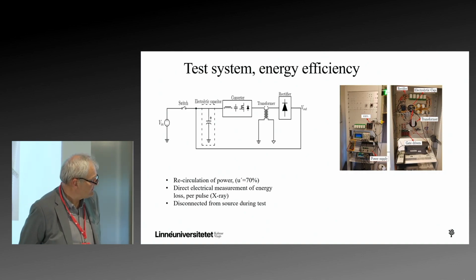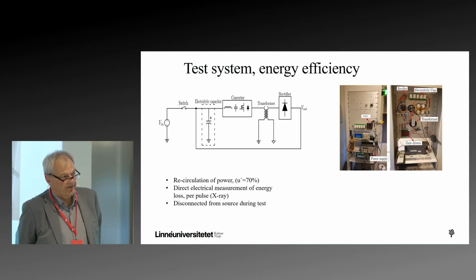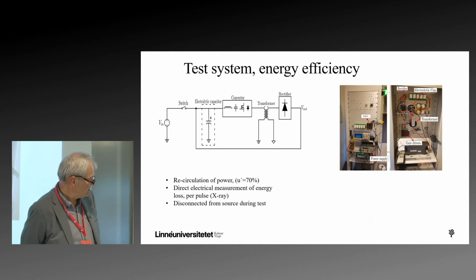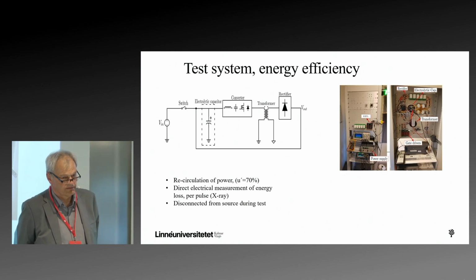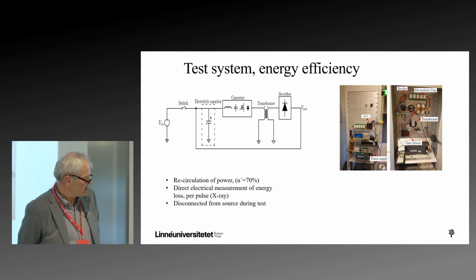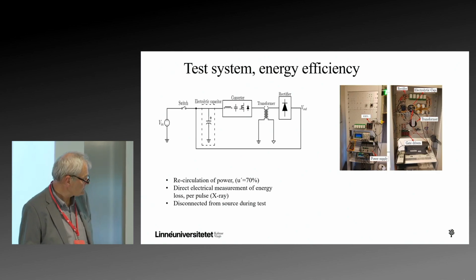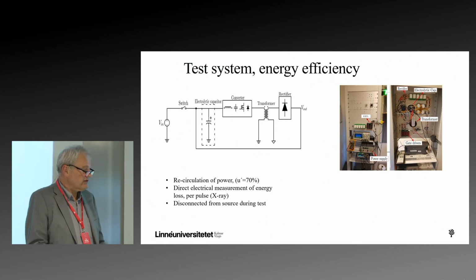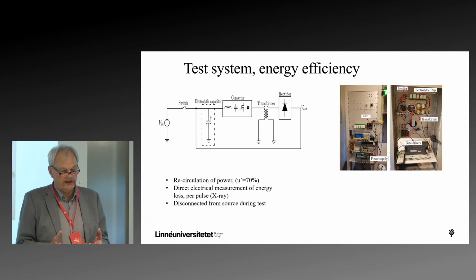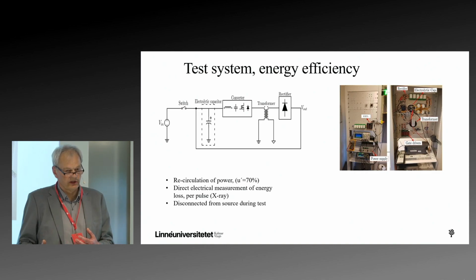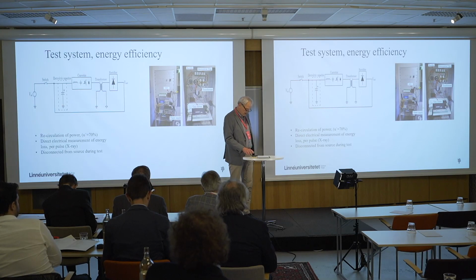Based on this, we built a physical test system to be able to, in pulse mode, evaluate the total system losses and be able to test with different switches, namely silicon IGBTs and silicon carbide MOSFETs. And since this system is designed to operate in a pulse mode, it cannot operate continuously. It will burn within 1 or 2 seconds. It is not designed to have a continuous operation.